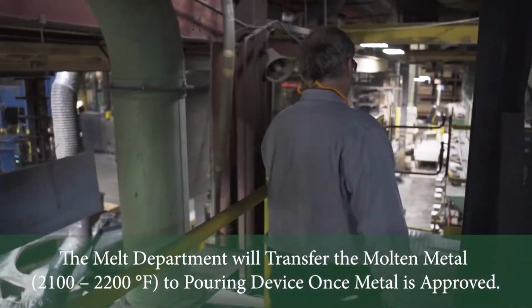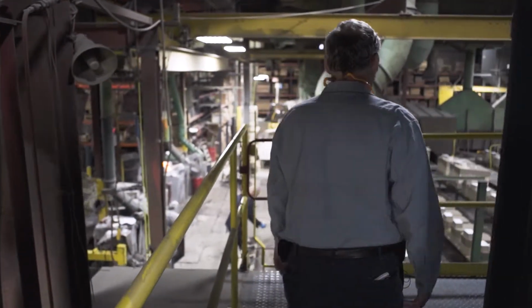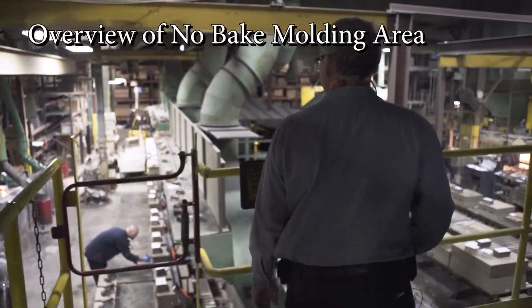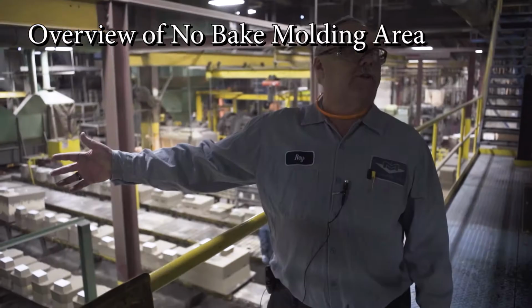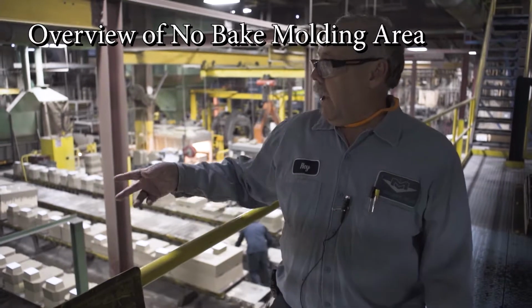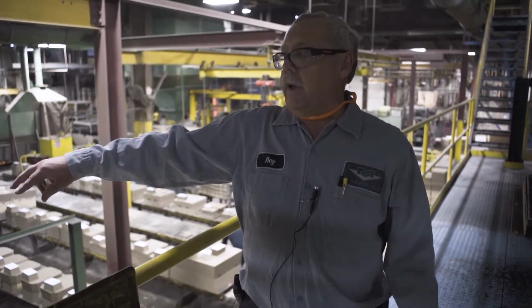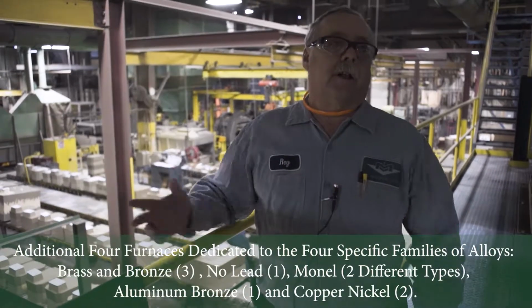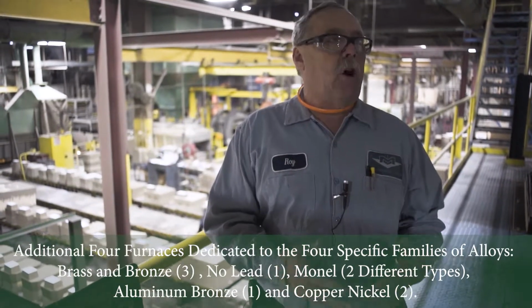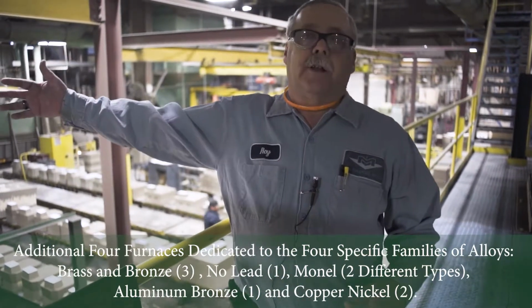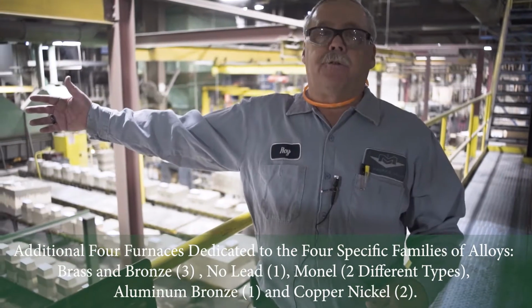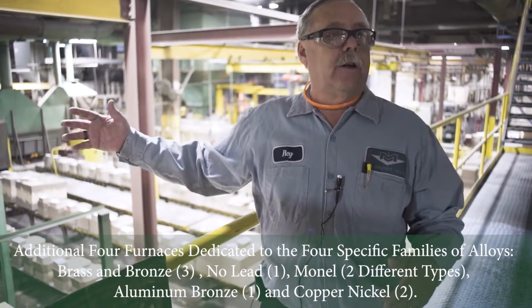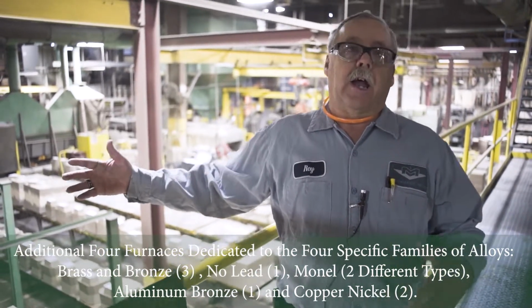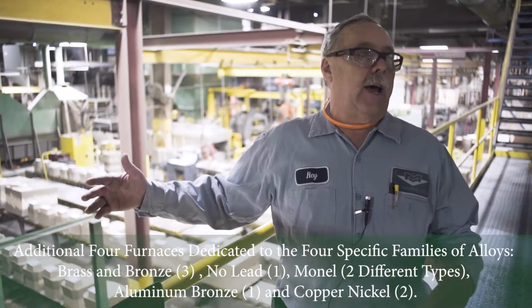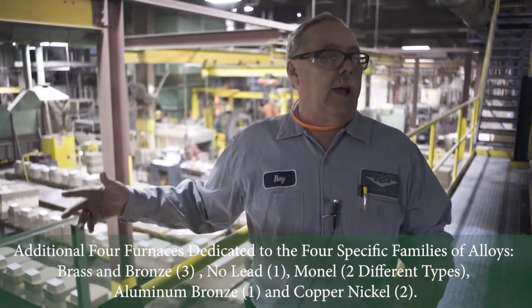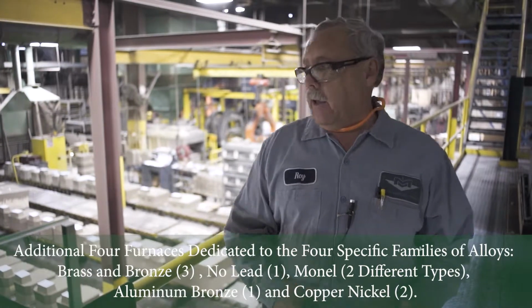I will go over and look at the no-bake area. In the no-bake area out here, we have some additional melting furnaces. We have 3,000 pound furnaces and 300-pound furnaces. They're dedicated to the different alloys we pour. We have a furnace for a group of alloys. We may have a furnace dedicated for the Monel, a furnace dedicated for the bronze, a furnace dedicated for aluminum bronze, and one dedicated for the copper nickel alloy.